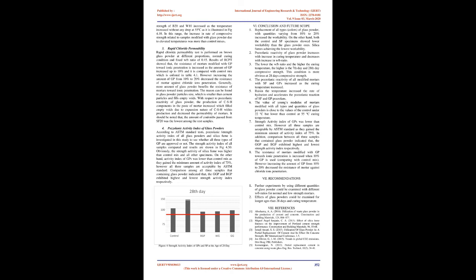Figure 5. Effect of different colors and quantities of GPs on 7 and 28 days compressive strengths for W/B 0.40 under 80 degrees C curing temperature. The comparison between all specimens that were prepared at W/B of 0.40 and different curing temperatures showed that early compressive strength of control mixture decreases as the temperature increases to 55 degrees C, then increases when the temperature rises again to 80 degrees C.